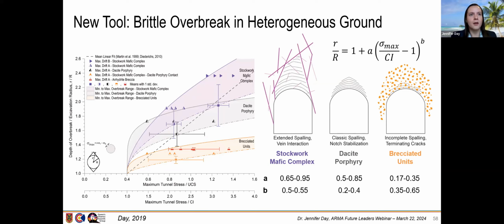The dacite porphyry exhibited fairly classic spalling. There was not much going on for geological heterogeneity, and there was sort of that notch stabilization, which aligned a bit better with that linear function. And then in the brecciated units, there was actually a lot less overbreak than what would be predicted by that homogeneous ground function. And we interpreted this as the breccia clasts themselves resulting in terminating cracks of spalling. And so the spalling was incomplete and not able to form and further develop.